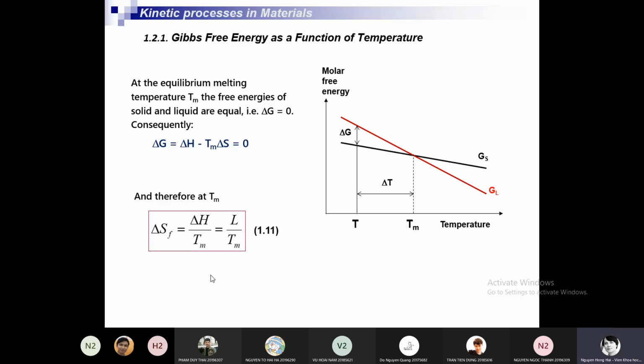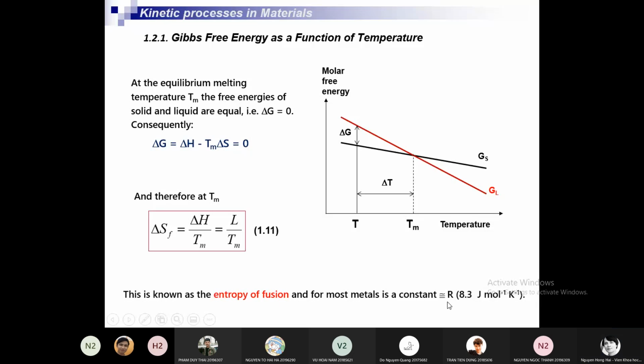Okay. And we introduce one more thermodynamic term, the entropy of fusion. Entropy at temperature Tm. So this is known as the entropy of fusion. And for most metals, this entropy of fusion is approximately equal to the gas constant, about 8.3 joule per mole per degree. So now we know the entropy of fusion.